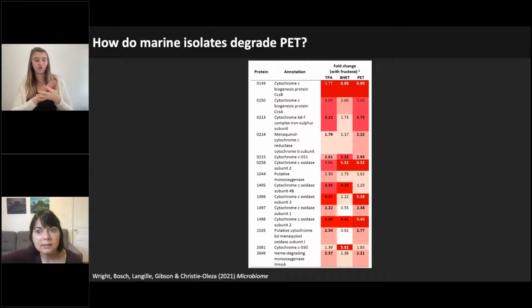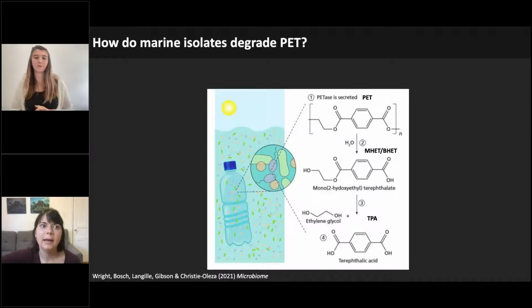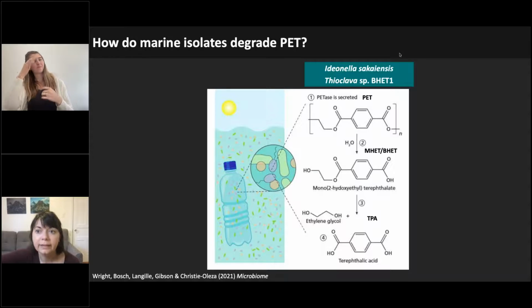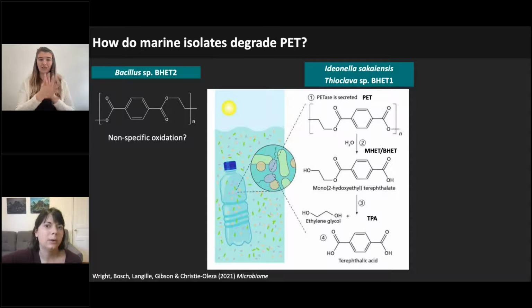However, in the case of Bacillus, there were no enzymes in the genome or the proteome that were homologous to those used for PET degradation in our known terrestrial PET degrader, Ideonella. But what we do find is a really huge number of oxidases and monooxygenases that are all far more abundant when Bacillus is incubated with the PET substrates than when it was incubated with our fructose control. So this kind of led us to hypothesize that perhaps rather than this pathway that both Ideonella and Thioclava use, maybe Bacillus just degrades PET through a lot of really non-specific oxidation.